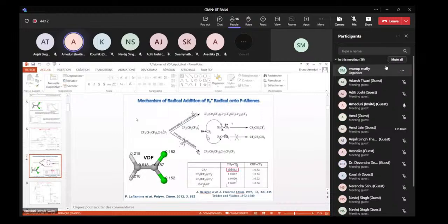However, in the case of trifluoroethylene, it's not so obvious, but you have this regioselectivity, and you can even have the possibility to get this addition of fluorinated radical onto the CF2. And this was very well evidenced also by polymerization or copolymerization of trifluoroethylene, in which you have a lot of reverse additions, much more than in PVDF.